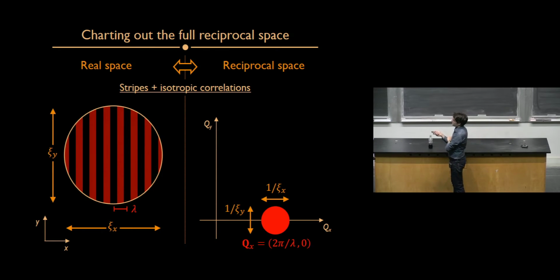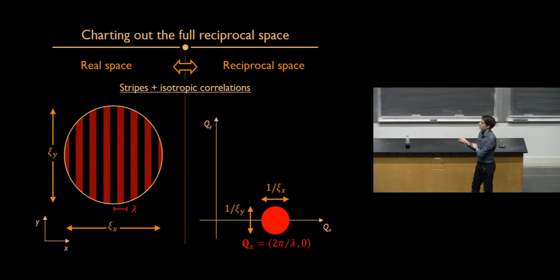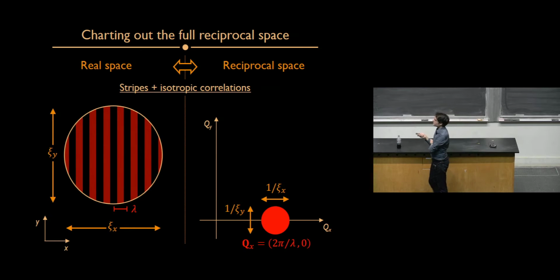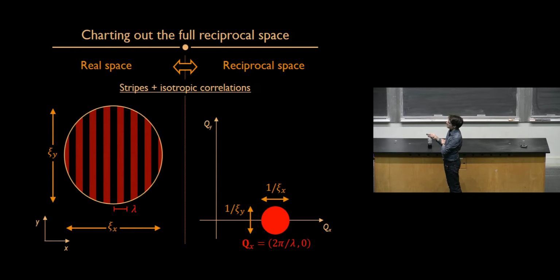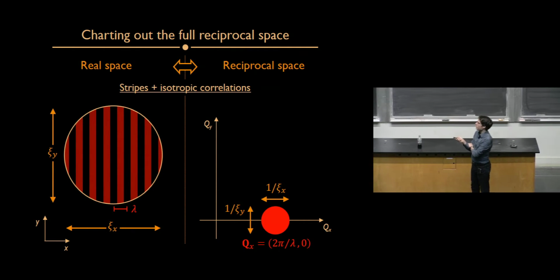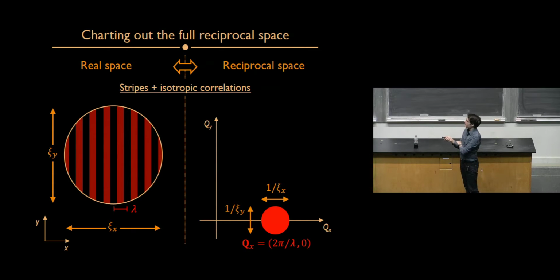So let me take a stripy domain. This is a circular domain with stripes. So if I take the Fourier transform of this guy, so this is the wavelength, let's say, so these are the crests of my sinusoidal kind of charge modulation. The crests are propagating in the horizontal direction, so I only have a peak along the qx reciprocal axis, right? This makes sense. I have no peak along qy. And I have a given broadening in reciprocal space, which reflects the fact that this domain has a real space coherence, which is only, let's say, a given number of wavelengths.